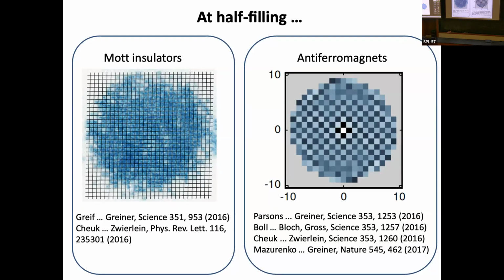You can also see the antiferromagnetic phase, which is another of these phases I mentioned at half filling. So here, what you have to imagine is this system at half filling at strong interactions. It has this 1 atom per site that are coupled through the superexchange. And it turns out the effective description is a Heisenberg spin model. So this is a quantum antiferromagnet with a lot of quantum fluctuations in it. So if you take the snapshots, you're going to have a hard time seeing the antiferromagnetism, but you can take these snapshots over and over and take an expectation value of the 2-point spin-spin correlation function. And lo and behold, you get clear checkerboard order emerge. So this is here the spin correlation function extracted from the snapshots.